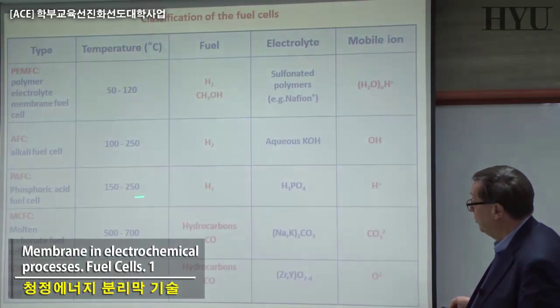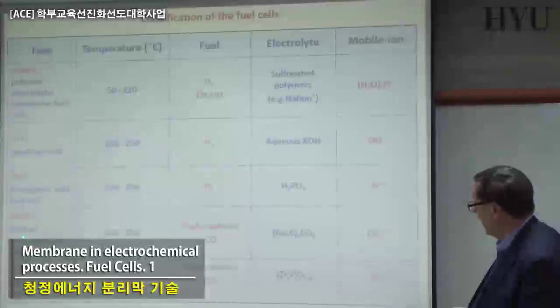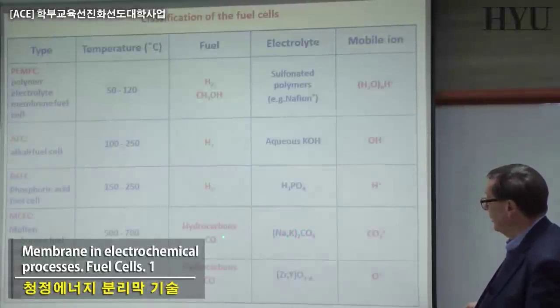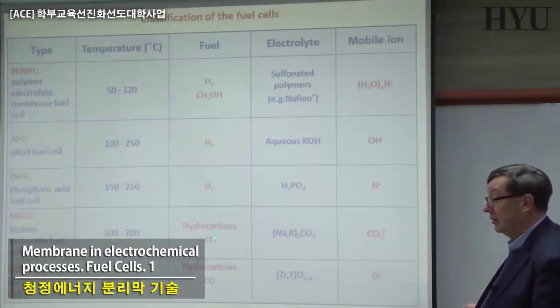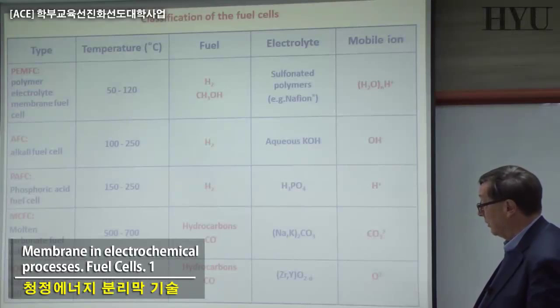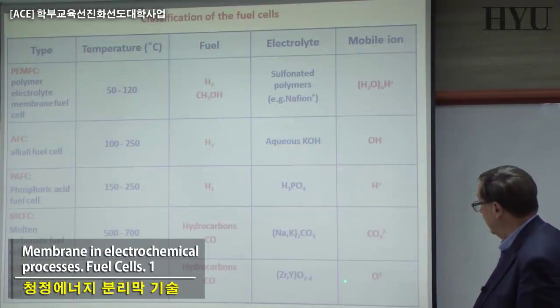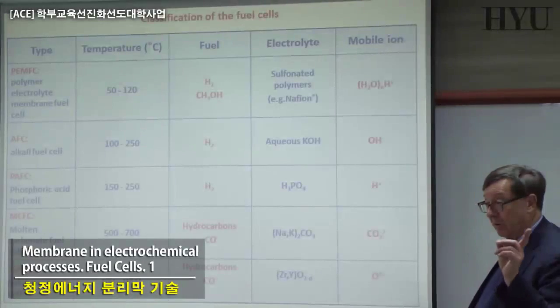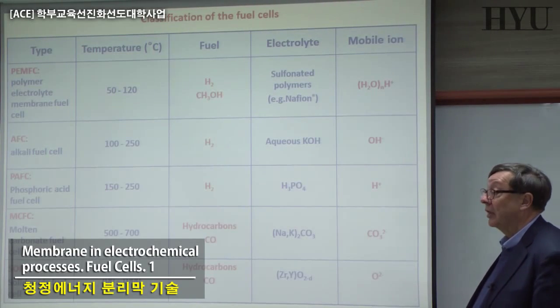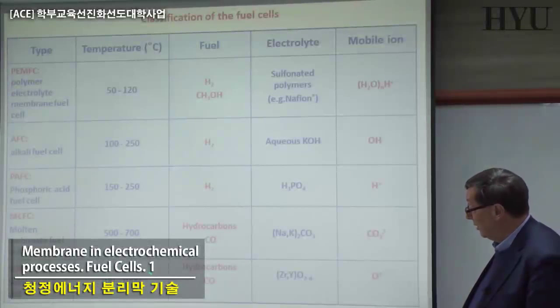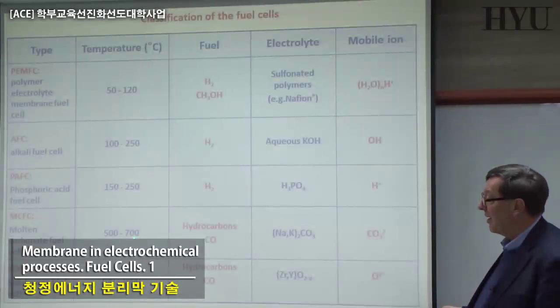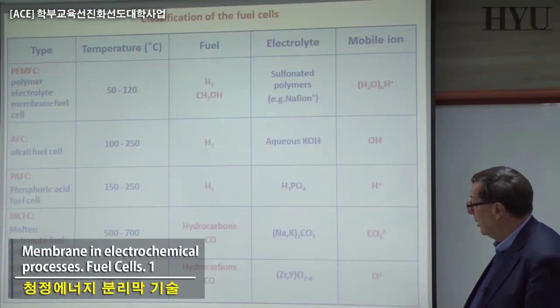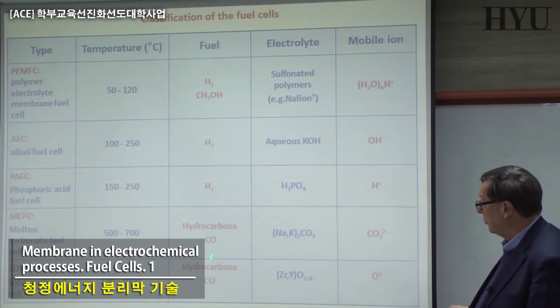Here is the same H plus, the phosphoric acid, and molten carbonate. This is just the molten carbonate. The hydrocarbons can be the fuel, or CO in some cases. The same here for this solid oxide fuel cell. And the solid oxide, remember we discussed already, mentioned also some perovskites, etc., can be utilized in this kind of system. You can see here, you have to activate at very high temperature, the same as when you want to melt this carbonate. But in this case, you can also use hydrocarbons as fuel.